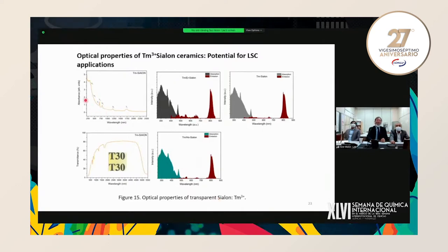So even in the UV area, we have some absorption, but in the visual light range not so big absorption. Also infrared, not much absorption. So the absorption is decreased and decreased. Also, we have a big Stokes shift in these cases, absorption peak and emission peaks.